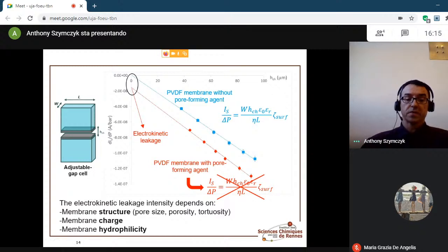This is of course obvious, since when the distance between the membrane samples is zero, then there is no streaming channel, and therefore no current can flow between the surfaces of the membrane samples. On the other hand, if the same type of experiment is carried out with a PVDF membrane synthesized under the same conditions, except for the fact that a pore-forming agent has been added to the polymer solution, we observe that the line no longer passes through the origin, which indicates that a current continues to flow through the measuring cell even if the two membranes are in contact.